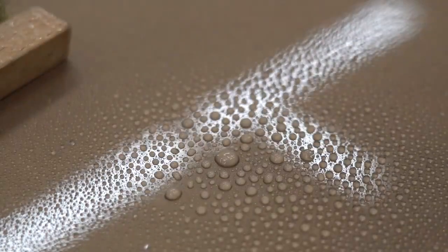Next, I take a brass brush and create surface scratches on the film and coating. As you can see, you can still scratch a ceramic coating, even when this has a scratch resistance of 9H, the highest rating on the pencil hardness test and the standard for a good ceramic coating. Next, a heat gun is used to heat up the surface, and as you can see, just like a non-coated XPEL paint protection film, the surface heals just fine. Again, it comes down to just how thin the ceramic coating is. So is the coating still there? A few sprays of water, and you can see the hydrophobic qualities of the ceramic coating remain.